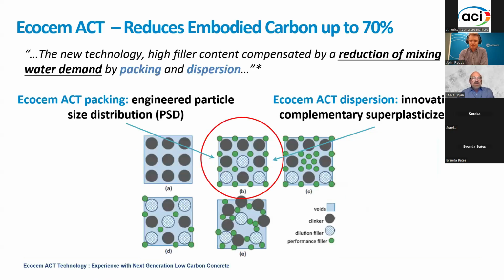And Ecocem has done that by focusing on engineered particle size distributions of all the constituents, which actually means reducing carbon content, separate grinding of all the materials. That's the only way that you can maintain control over the particle size distribution of all the constituents, is to separately grind them, then blend them. And then at the same time, we pair those with complementary superplasticizers. Once the composition of the cement is significantly changed from a clinker basis to a variety of different SCMs and different mineral admixtures, there's a need to adapt the superplasticizer molecules in order to get the same performance cost effectively.